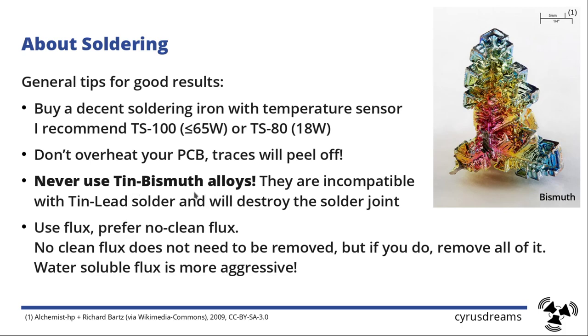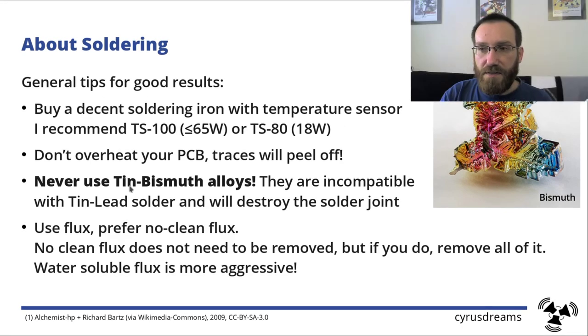They have a lower melting point than tin silver copper alloys, SAC, which is the more common type. But the bismuth, which is a nice crystal forming metal, a really nice picture, that one really makes problems together with tin and lead, because tin, lead and bismuth together give you Rose's metal, which has a melting point around boiling water temperature. And the solder joints would be very, very brittle and they will fail very fast. So don't buy that stuff.